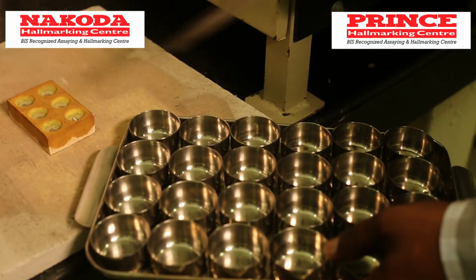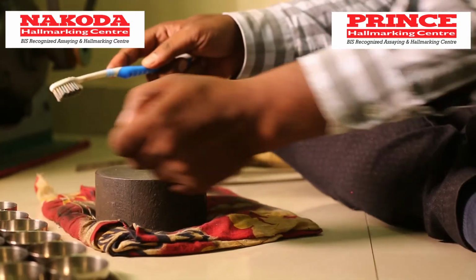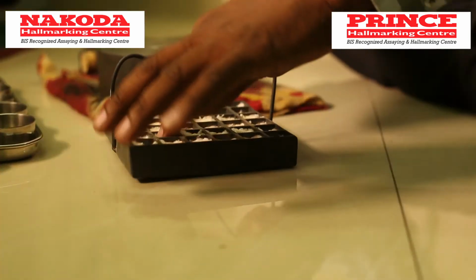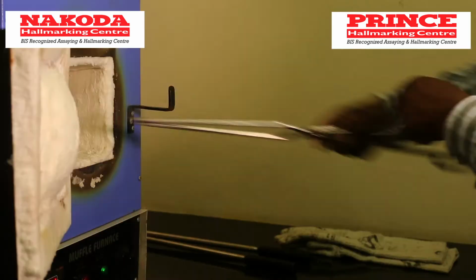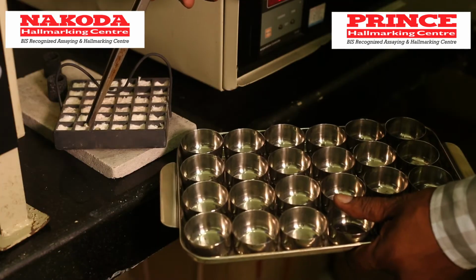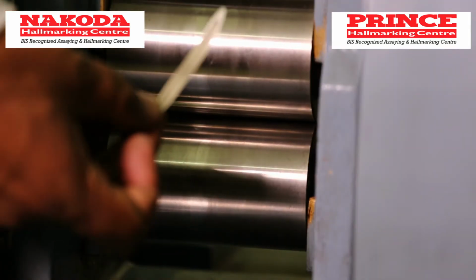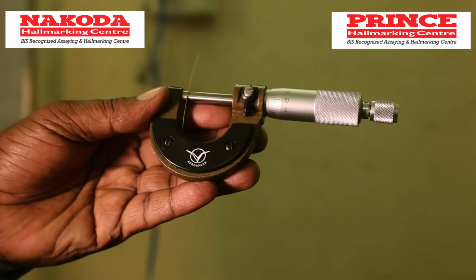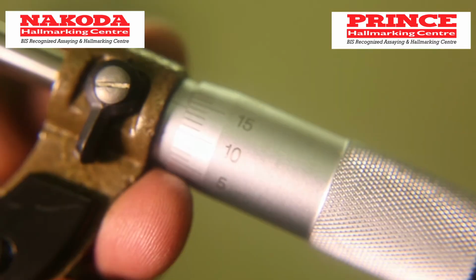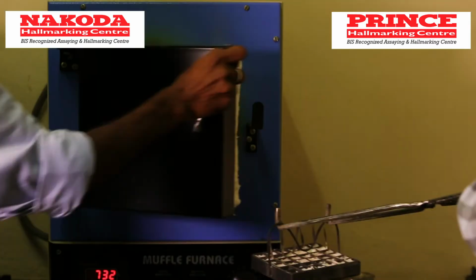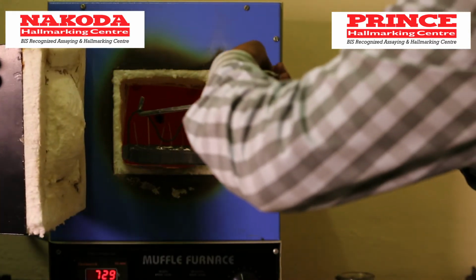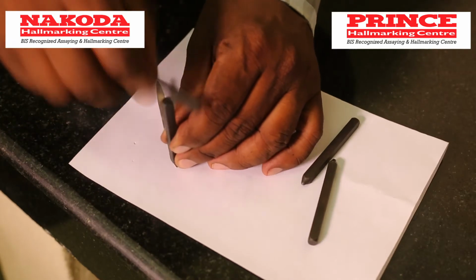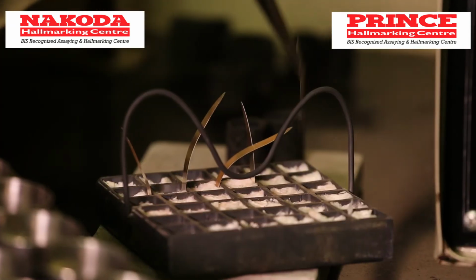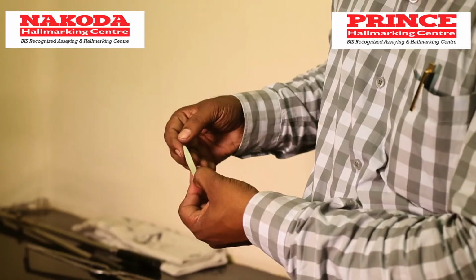These small balls are then taken out, cleaned, flattened and annealed. They are then rolled to form strips once again. The strips are then checked for thickness, which has to be uniform for proper testing. Then the strips are annealed and numbered so that they don't get mixed up in the further processing.